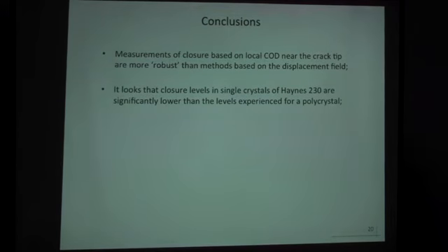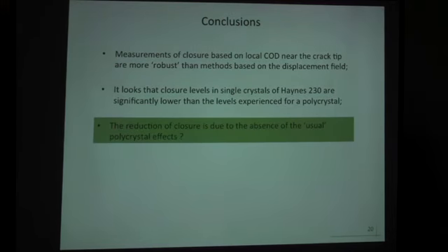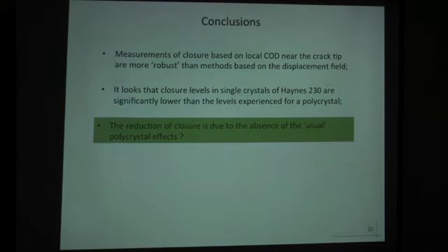It looks like closure levels in single crystals are significantly lower than the ones of polycrystals, and this is not a conclusion, but rather, I would say, a starting point of an activity. I would say it is an opinion, but it's open for discussion, that perhaps this reduction of closure is due to the absence of those phenomena like roughness or different grains that we are used to having in polycrystals.